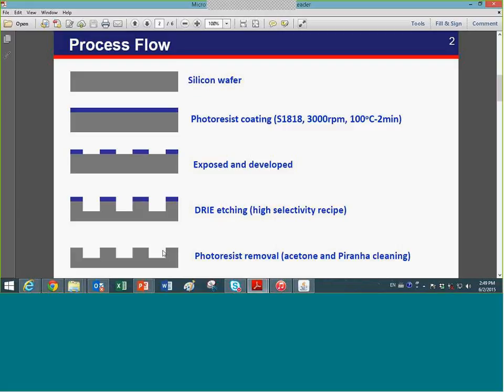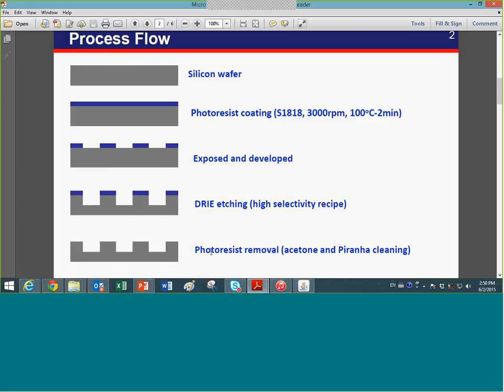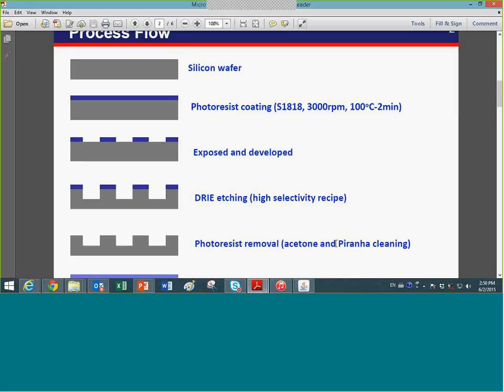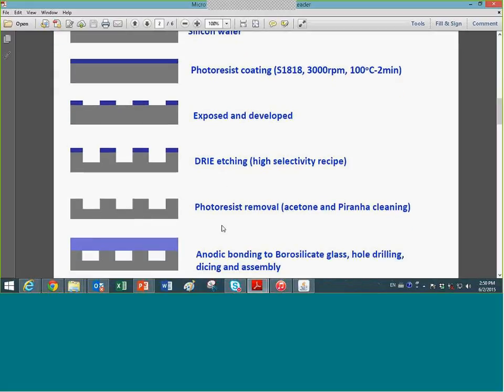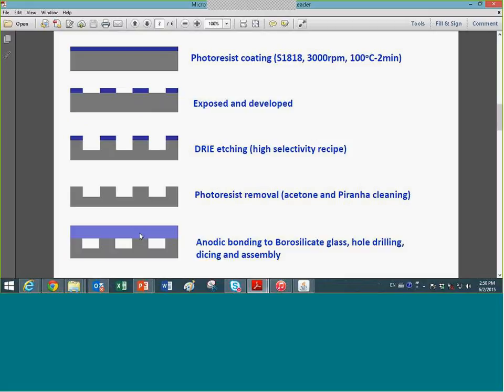Depending on the application, we can control the depth of the channels. In most of the applications, they just need to dig down to 200 micron channels. After the etching, just simply remove the resist and then use piranha to clean the wafer, and then anodic bonding with a borosilicate glass. And then you drill the holes to feed the microchannels, dice, and then assemble for the test.